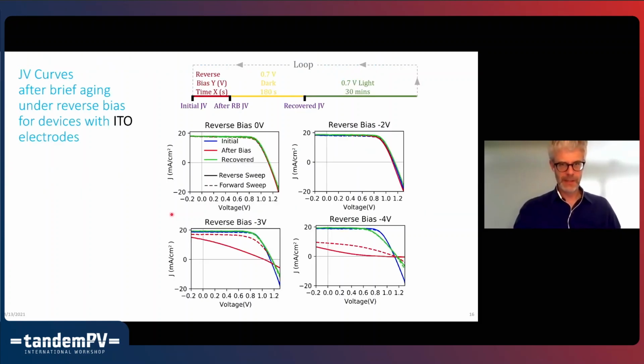So we've studied those a lot, and now our protocol is a bit more advanced than just running an IV curve in reverse bias. We pick a reverse bias voltage, and then we'll hold it there for typically 30 seconds or a minute. And then we find that when we go back into forward bias, under light, the efficiency will be reduced, but we do find that a lot of it recovers. So a typical recovery protocol is a few minutes in the dark at 0.7 volts, and then a half hour under light. And then we remeasure the IV curve.